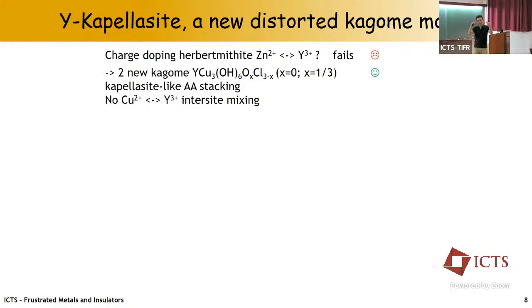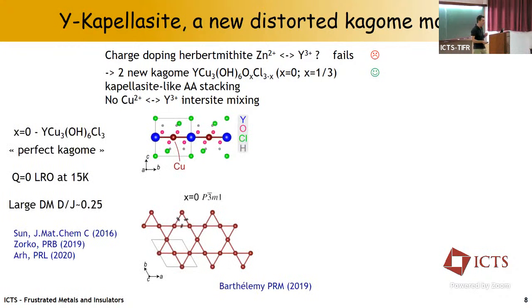So from the structure of Herbertsmithite, you go to the structure of kapellasite. It's also a Kagome structure with a simpler stacking, actually, and a more 2D structure. And you end up with two new structures, the so-called x equals 0 and x equals 1/3, and I'm going to explain a little bit what they are. So the x equals 0 material is actually a perfect Kagome. It shows a perfect Kagome lattice.